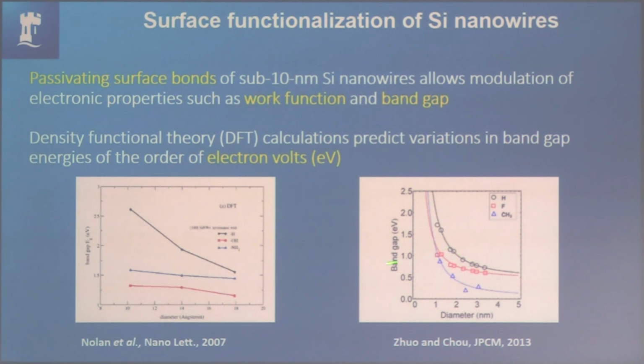So anyway, this is some calculations we did a long time ago and some other people have done. Actually, there's other people who have done this. But it's basically take a silicon nanowire, put hydrogen on it or put a hydroxyl on it or an NH2 or whatever. And what happens is you get the quantum confinement effect, and that's what you're seeing here. These all have band gaps much larger than bulk silicon, but the actual surface chemistry, due to its electronegativity and the large surface to volume ratio, counteracts the quantum confinement effect. So the more electronegative you make your surface passivation in silicon, you can tune that band gap.